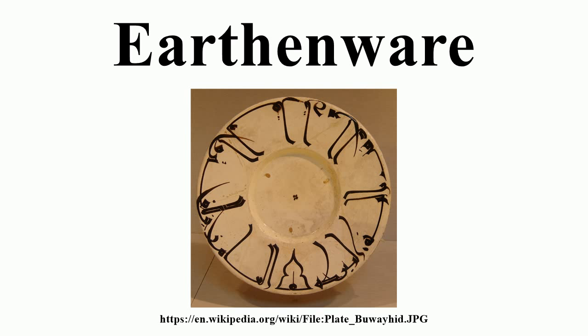Earthenware may be biscuit-fired to temperatures between 1000 and 1150 degrees Celsius and glost-fired to between 950 and 1050 degrees Celsius. This is the usual practice in factories and some studio potteries. Some studio potters follow the reverse practice, with a low-temperature bisque firing and a high-temperature glost firing. The firing schedule will be determined by the raw materials used and the desired characteristics of the finished ware.